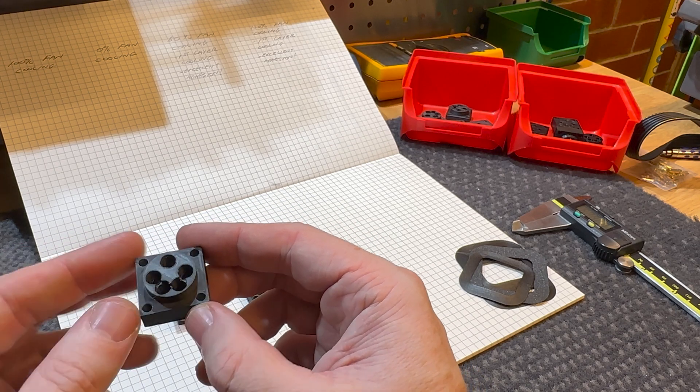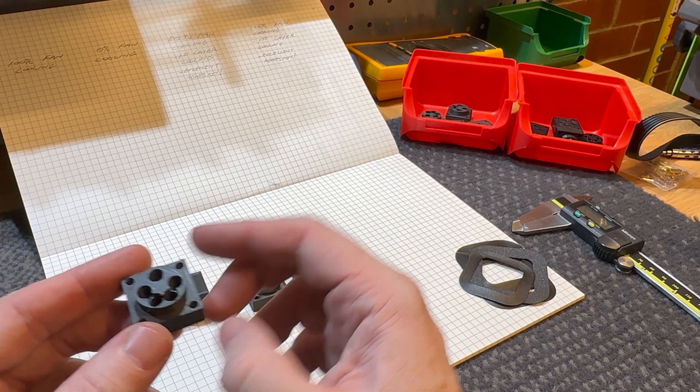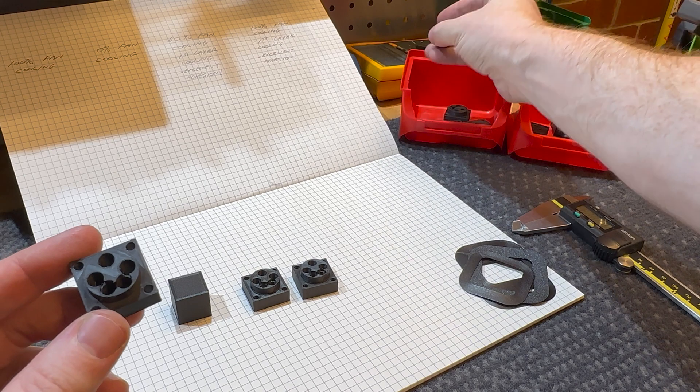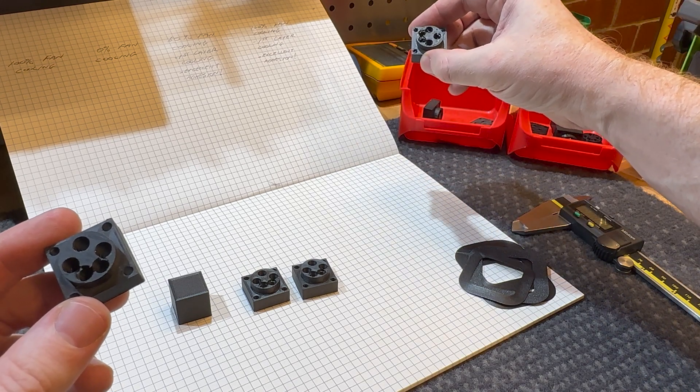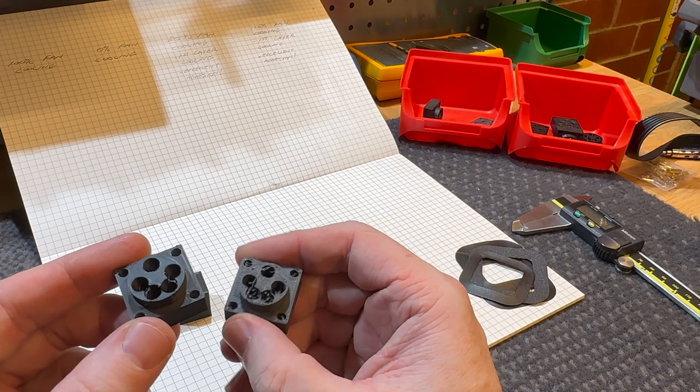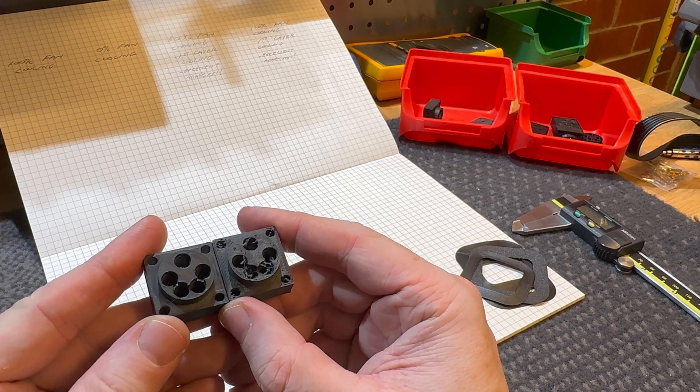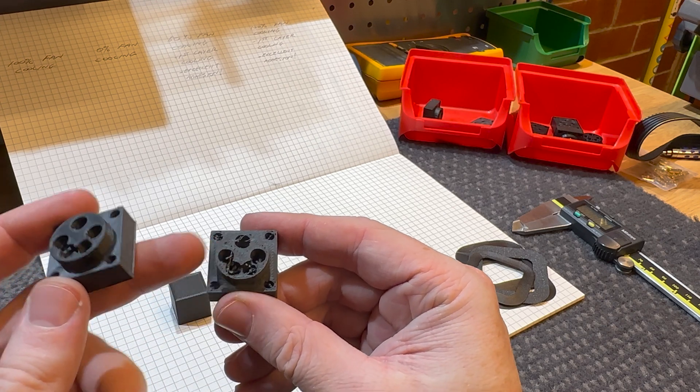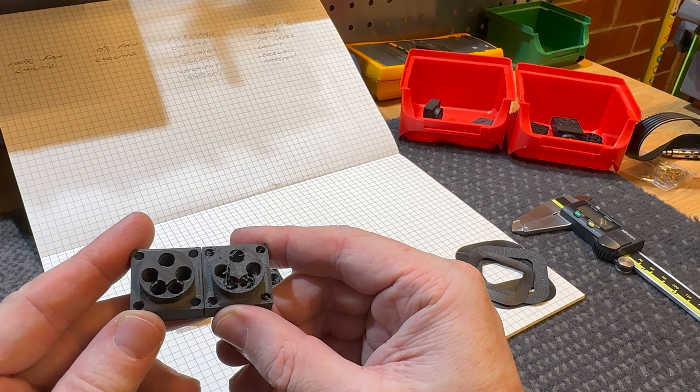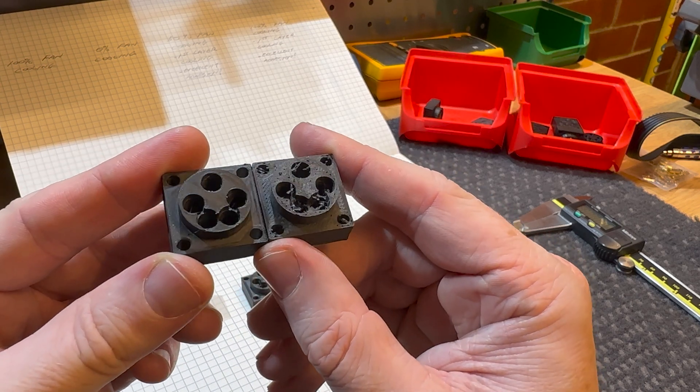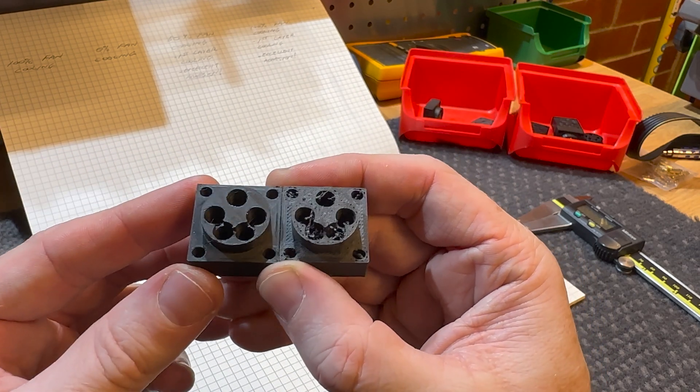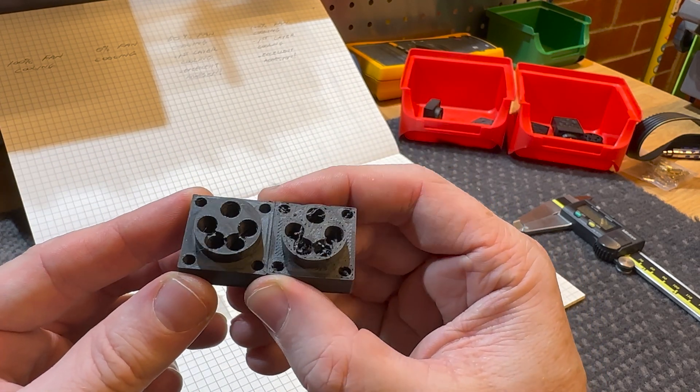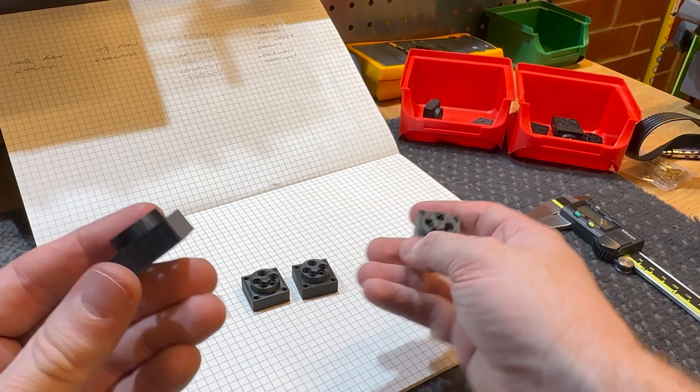And I find the porosity or the holes that you get in the top is quite a problem with carbon filament. If I grab one of these old test prints that I did on the old machine using the eSUN CF filament, you can see the difference here. It can barely maintain any sort of fine detail. The Markforged part—sorry, using the Markforged filament—is just vastly superior, and I'm really impressed with it. This stuff is excellent.